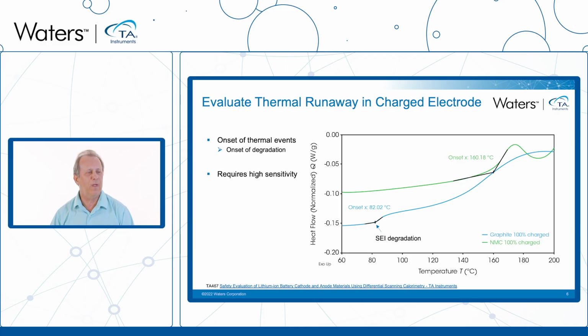And so in this slide here, we see that actually it's the anode material that begins to decompose first. Around 82 degrees Celsius, there's an onset of exothermic activity, and that actually is the degradation of the SEI, or the solid electrolyte interface. So even though the cathode material has more energy release and a more complex transition, it's the degradation of the SEI early on the anode side, which begins to drive these reactions moving forward. And to capture the SEI degradation, you need an instrument that has very high sensitivity and a very good baseline, which is what the Discovery DSC 2500 does have.